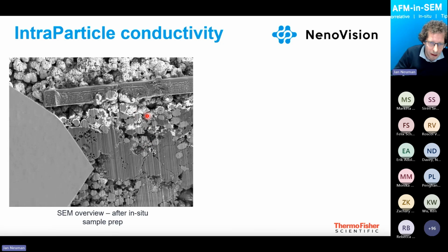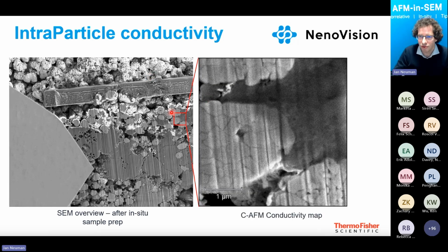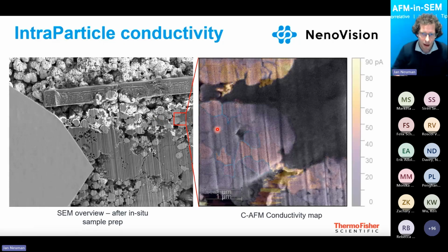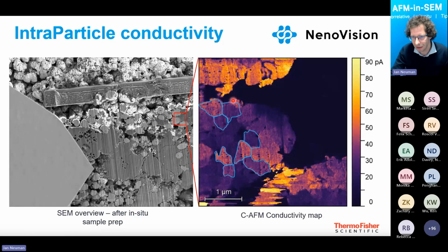So this is the schematic of how you can see it. These are the particles or cathodes which we can select for the analysis. This is the AFM tip. This is the area which we have selected for the analysis, and then again we can correlate it with the conductivity map, and directly we can see how different grains reveal different conductivity. So again, it is very important how the material is behaving before the cycling, after the cycling, etc.